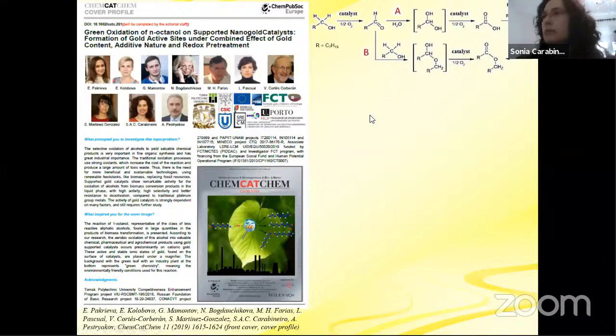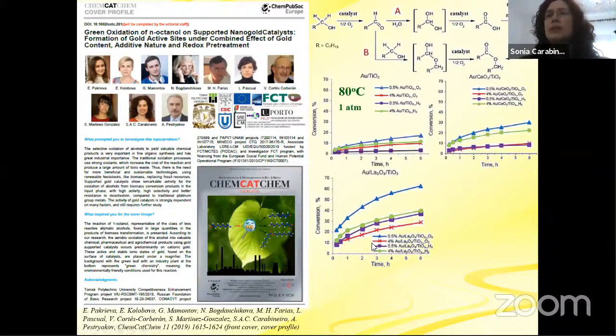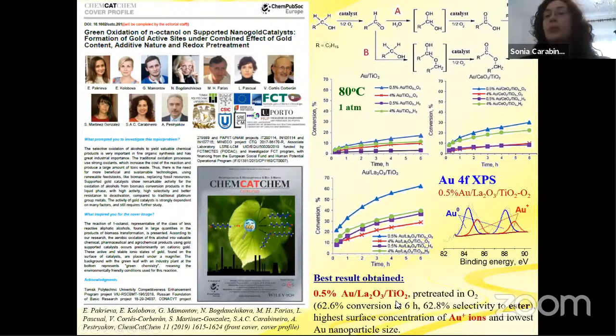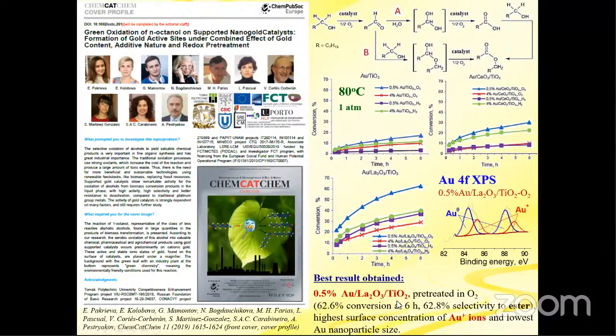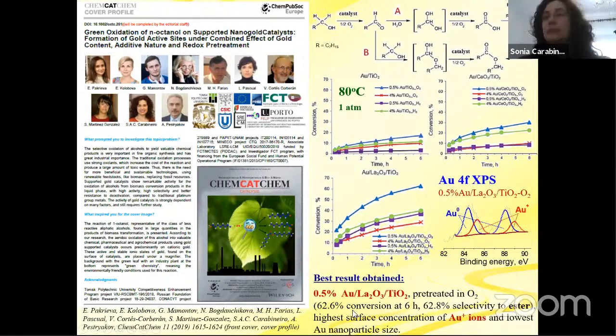So it was performed at 1 atmosphere, atmospheric pressure and 80 degrees Celsius. And we see that the best result here was 0.5% gold on lanthanum oxide/titania catalysts pretreated in oxygen. So it was a 62% conversion at 6 hours and 62% selectivity to ester. And this catalyst has the highest surface concentration of gold plus ions, so gold 1, and the lowest gold nanoparticle size that gave these results.